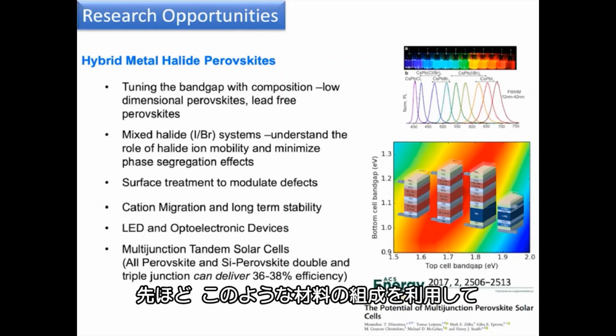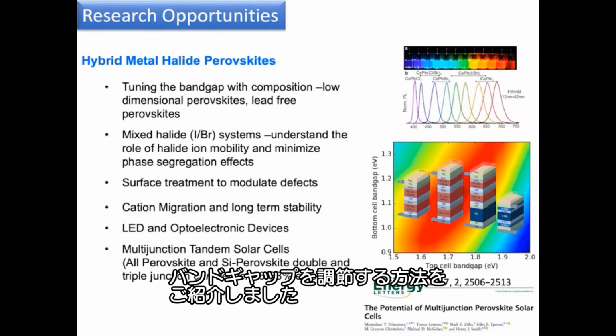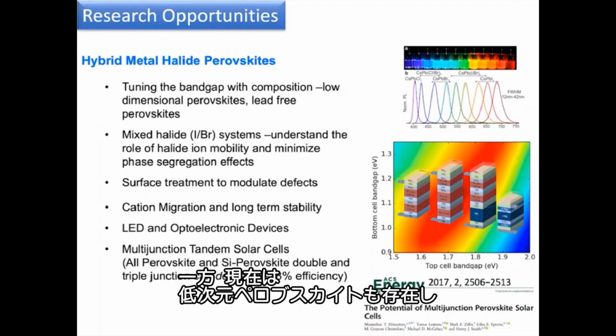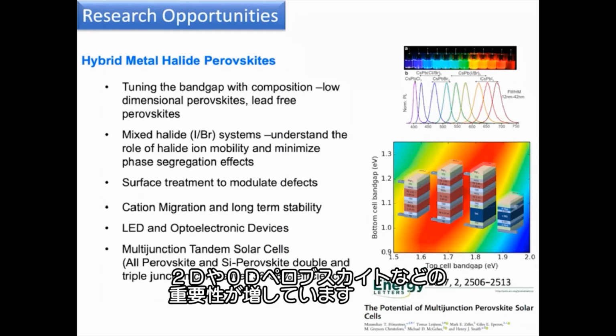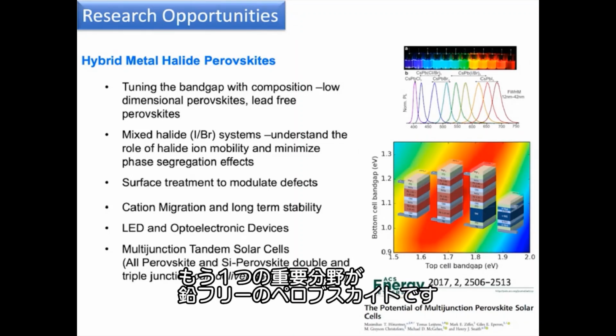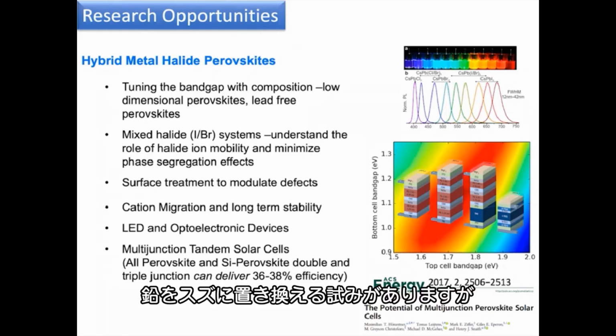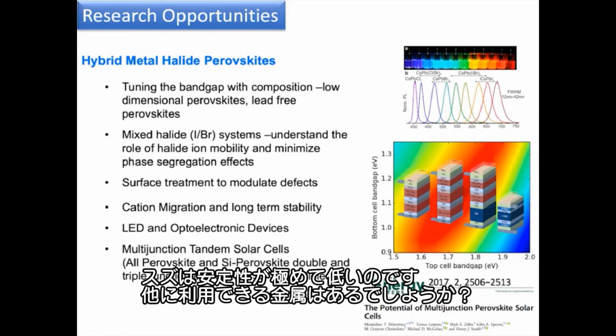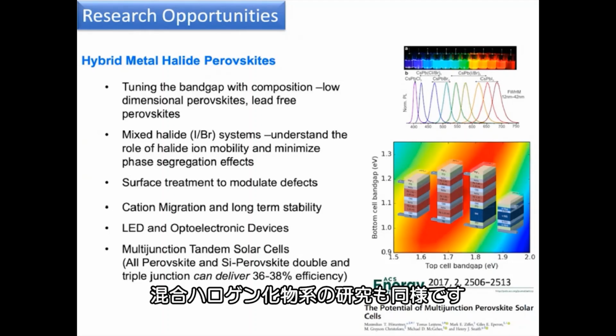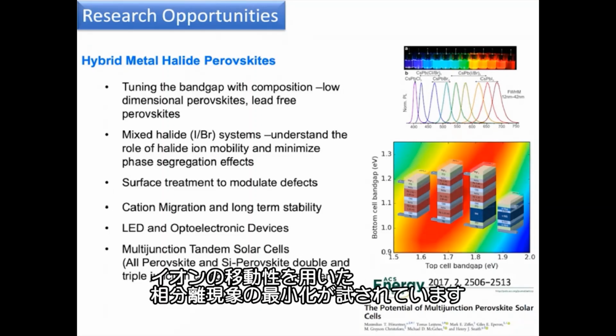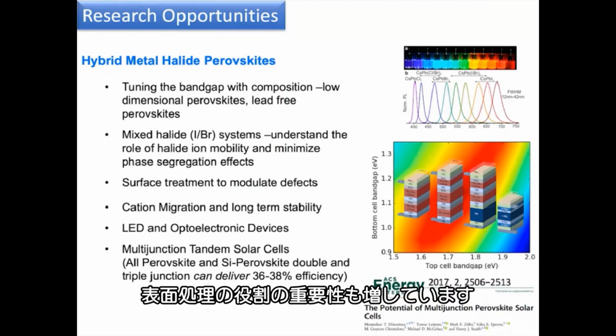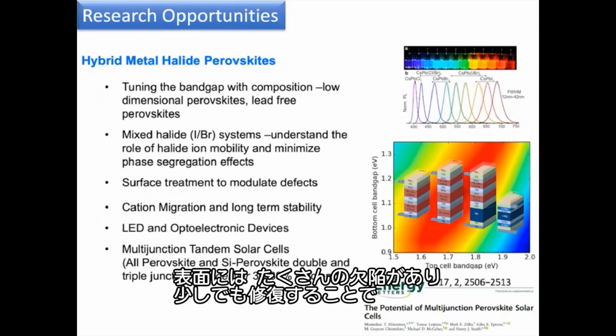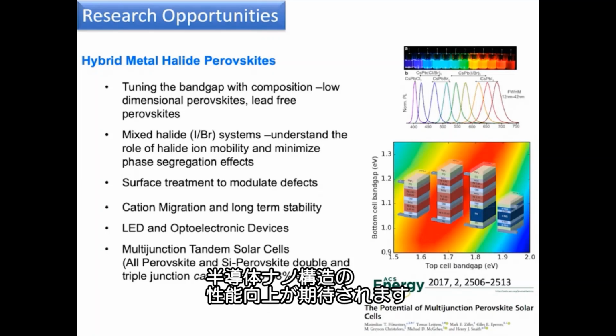I just mentioned to you how we can tune the band gap with composition with these materials, but there are also now low dimensional perovskites like 2D and 0D perovskites, so they are coming into play. Another area that is important is lead-free perovskites. People are trying to replace lead with tin, but they are highly unstable. So are there any other metals that one can use? Same way, mixed halide systems, trying to understand the halide ion mobility and minimize the phase segregation effects. Surface treatment is known to play a greater role because it has lots of surface defects, and any remediation of these defects leads to better performing semiconductor nanostructures.